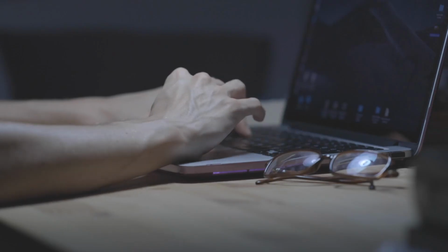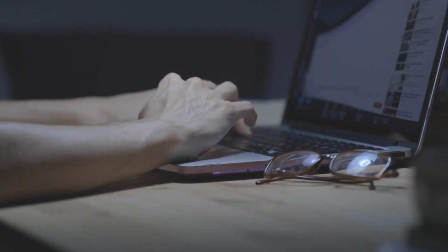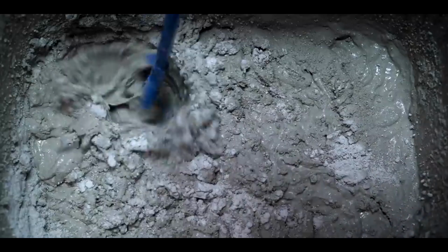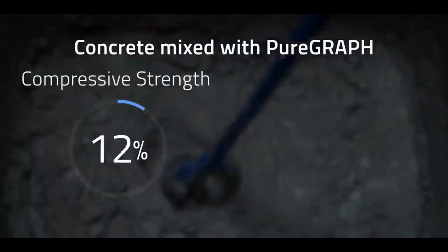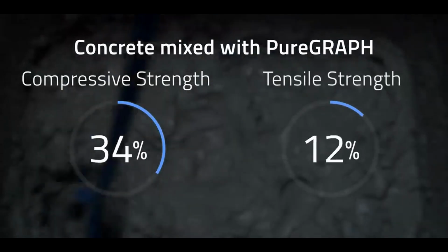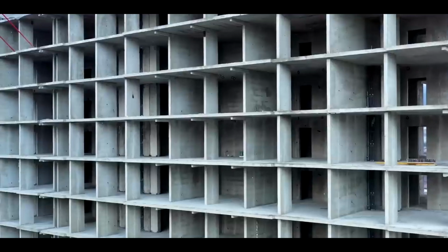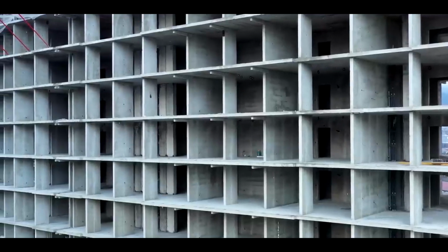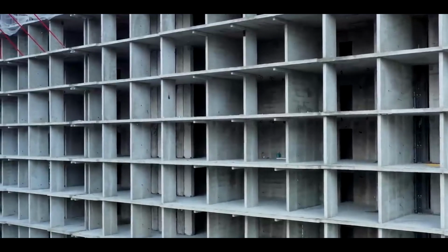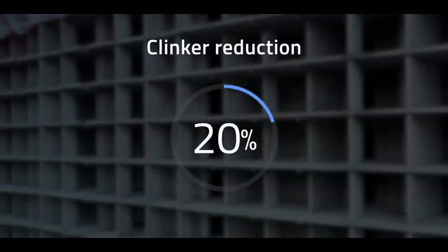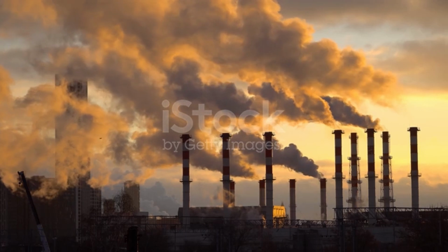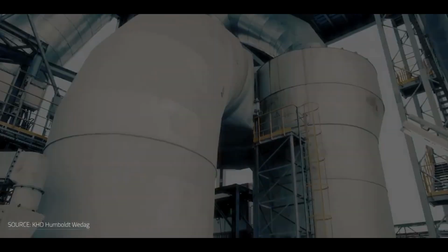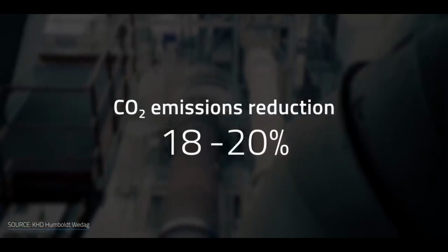According to a case study made by the company, when tested to international standard methods, product increases the compressive strength of concrete by 34% and tensile strength by 12%. On top of that, it extends the life of reinforced concrete structures because it avoids corrosion and also reduces clinker by 20%. This is where that CO2 reduction comes into play because of how it helps with clinker. CO2 emissions can be reduced by 18% to 20%.